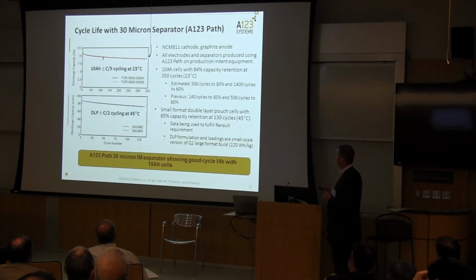Cycle life has also gotten a lot better. So again, these are on our production intent cells. We should be at about 500 cycles. Again, this is at room temperature to 80% capacity, and we're projecting to get over 1,400 to 60%. This is a substantial improvement from where we were last summer.